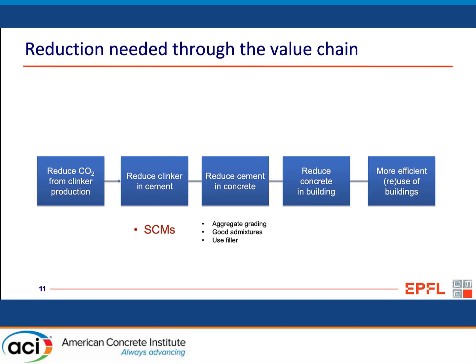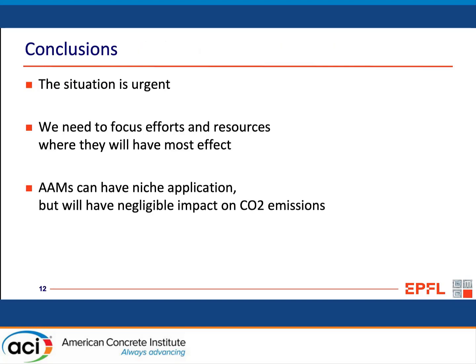And if we really put our minds to it, we can reduce the carbon footprint of cement and concrete by something like 70 or 80%. Now, that's not going to zero, and it means we're still going to have some CO2, which needs to be captured in some ways, either in some other process, which is carbon negative, or by biological means, by planting trees, or by carbon capture and storage. But as I said, these are very expensive, and we can save ourselves a lot of money down the line by doing the easy things first.